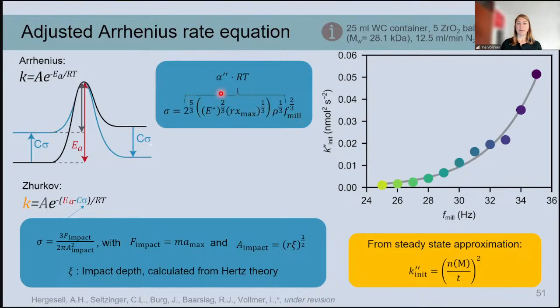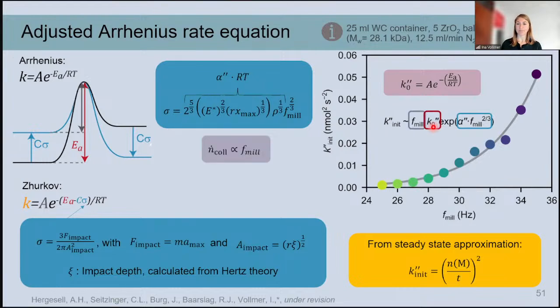And so this whole term, we do not change in this experiment, just the frequency. And so this is the constant times RT, as you can see here. And this is then the formula that we used for fitting this data. And so part of it is the activation energy barrier of the thermal part of the reaction, so this E_A, plus the pre-exponential factor, and we just combine this into a constant for fitting because we are not changing the temperature in these experiments. And then we also have to include something about the number of collisions that we also increase with the milling frequency. And as you can see here, this formula can actually fit this data quite well.